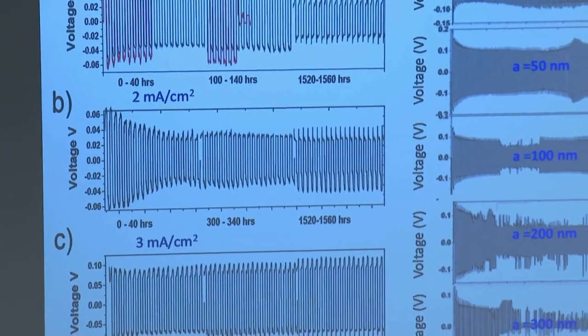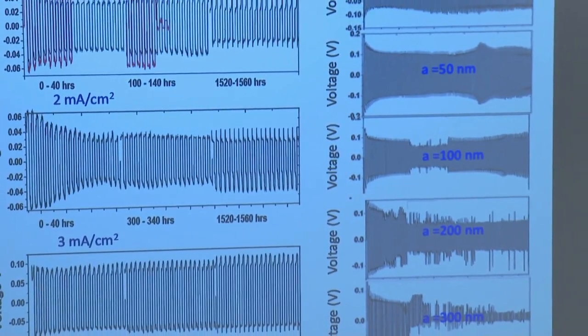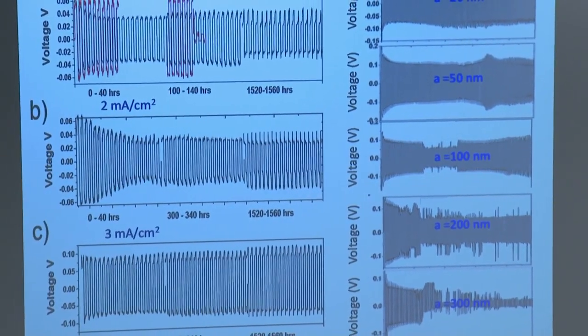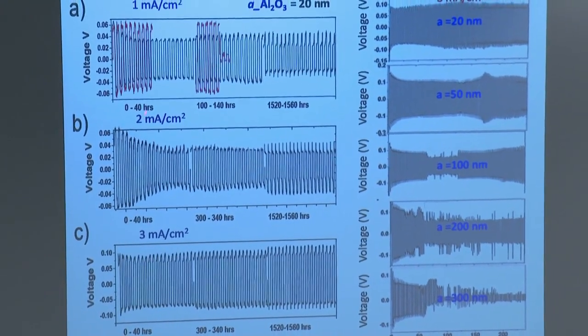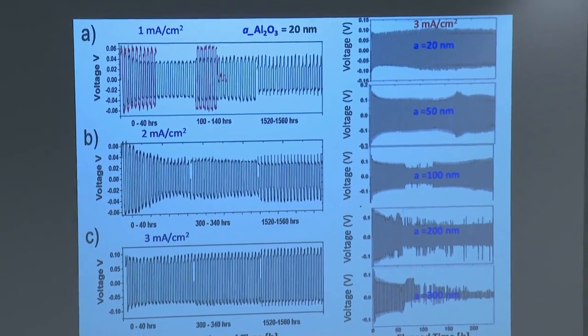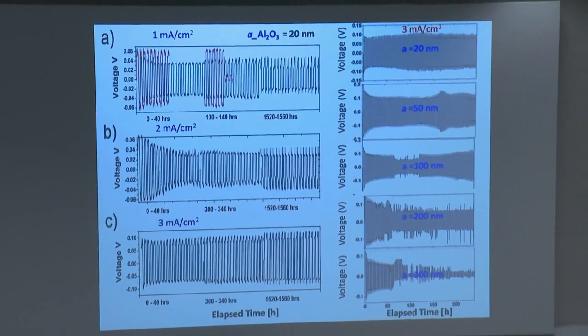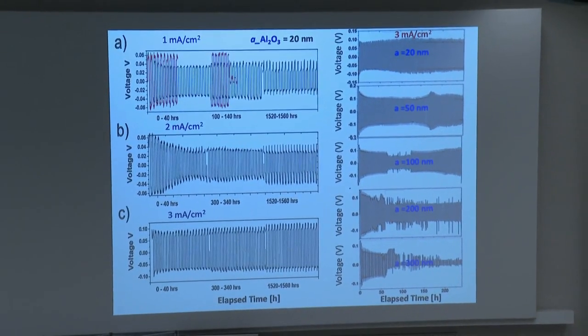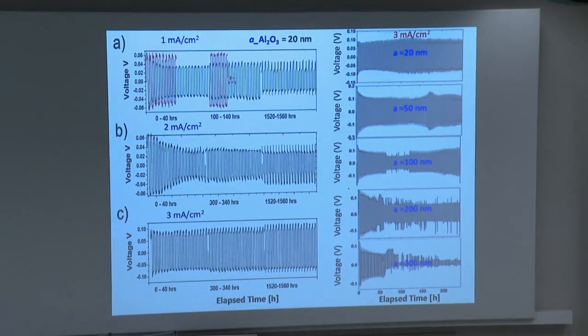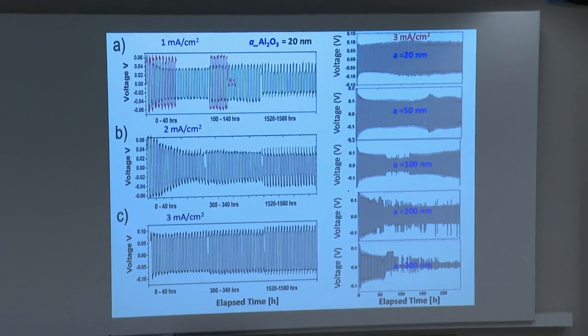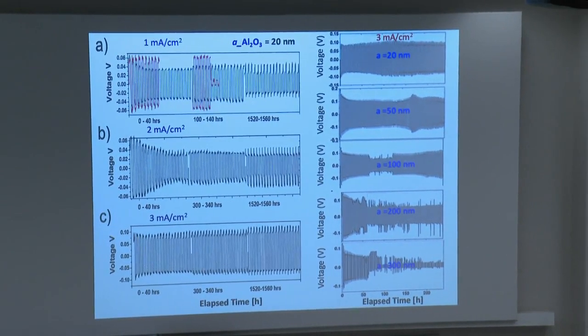okay? So I wanted to make this thing fail, okay? Because we had to know when it fails. So we increased the current. We increased the current to values that are not even normal, at least at that time, in lithium cells, and you can see it just goes on and on, indicating that we've completely eliminated the propagation and proliferation of the dendritic bumps in these systems.